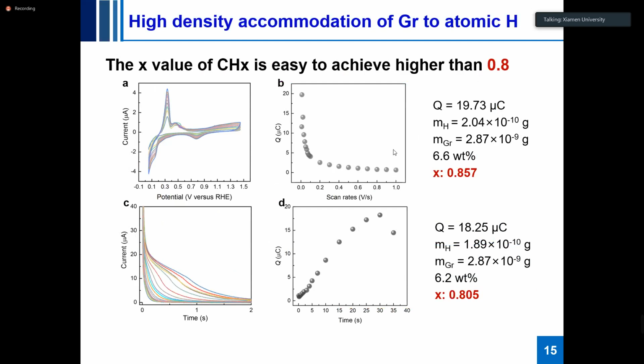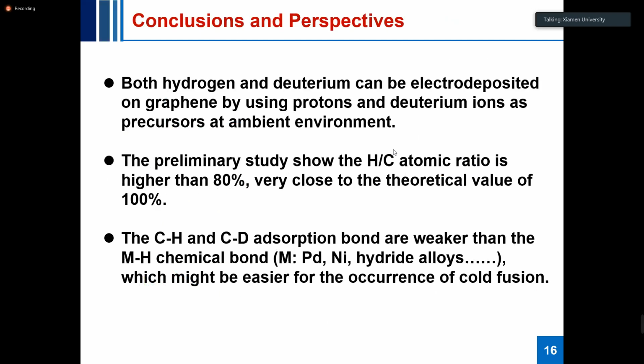We can also measure how much hydrogen can be adsorbed on the graphene. We perform the cyclic voltammetry and also the potential step experiment. From the maximum of the stripping charge, we can calculate that the X can be easily higher than 0.8. So this is the main conclusions and perspective.